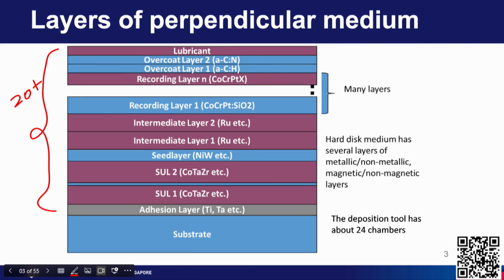Okay, so, these are the soft magnetic materials I described. The head produces a certain magnetic field, it goes through the soft underlayer, then goes back to the other side of the head. Okay. So, you notice that this soft underlayer is not a single layer, it is again a SAF. Okay, so, you have a thin layer of ruthenium and at least 2 ferromagnetic layers which are antiferromagnetically coupled. So, here again we are using a synthetic antiferromagnetic structure to minimize some noise, which we do not go into detail. Then we have some seed layers which help these ruthenium layers to grow with a certain epitaxial texture.